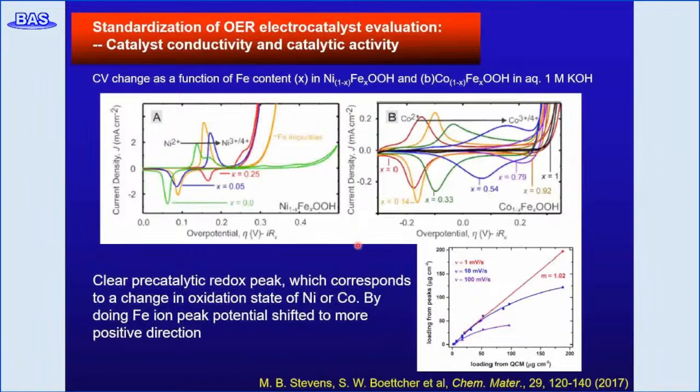It is important to know whether all the modified electrocatalyst solids are electroactive or not. The deposit amount of the catalyst on the electrode was obtained from the QCM measurement, and from the CV peak areas, the amount of charge, which corresponds to the amount of the electroactive catalyst, can be estimated.